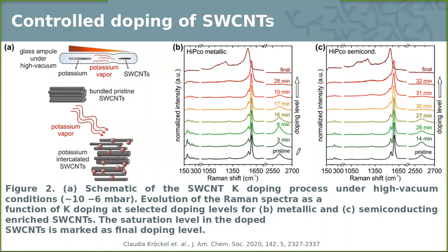This is actually a behavior that is really well known. The 2D line disappears because after a lot of electrons are present on the sample, you displace the Fermi energy level high enough so that the double resonance process doesn't exist any longer.